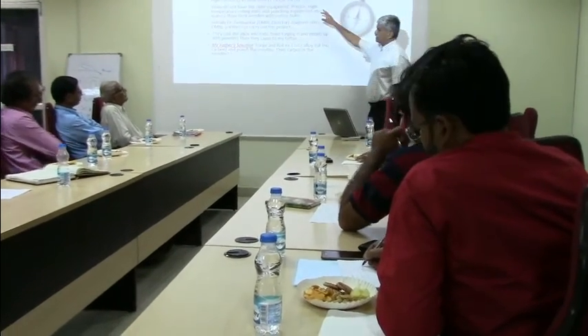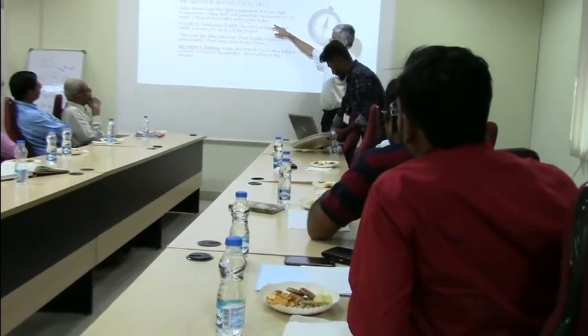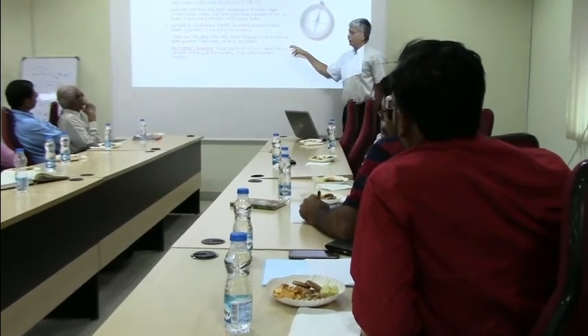We did not have the equipment in terms of precise high temperature rolling mills and punching equipment to make 2 thou thick. The 2 thou, I don't know if people still use thou, thousandths of an inch, which is 50 microns, right? Thick with center holes. Initially, Dr. Kamankar assigned another DMRL scientist to carry out the project. They cast the alloy into rods, they tried forging it, and they ended up with powder. And that's when they came to my father.